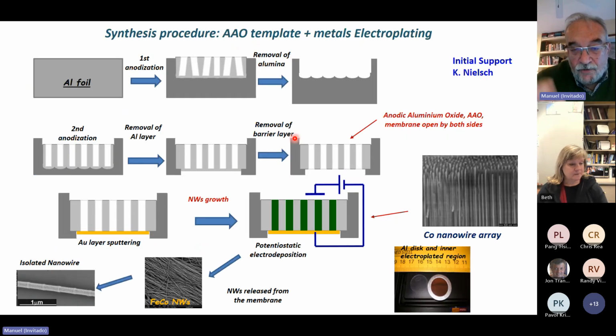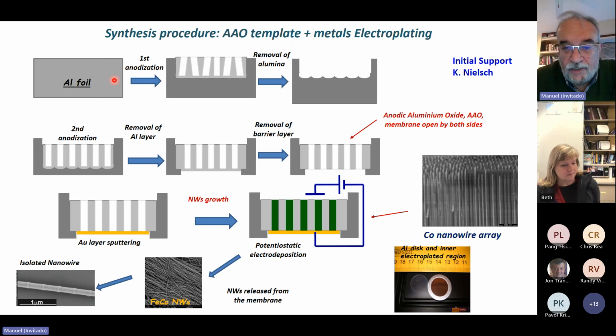This is a schematic view of how we prepare them. We start with a commercial aluminum foil, 1 inch in diameter, which has to be very pure, at least five nines in purity. After two processes of anodization, we get a membrane which is open at both the upper and the bottom. Then we sputter a tiny gold nano layer, and then we electroplate. This gold nano layer serves as an electrode for the electrodeposition. This is a picture of a hexagonal array of cobalt nanowires.